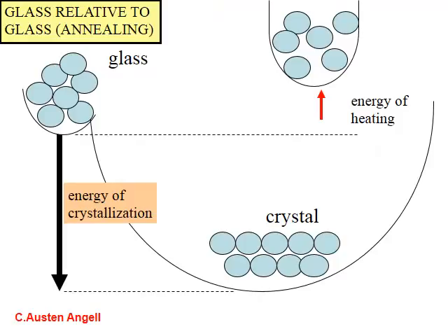Once obtained by quenching the melt, it's a common practice in glass production to bring the glass to a high temperature again, below Tg, in order to relax. Annealing is a routine operation in the preparation of glasses. The structure needs to mechanically relax. A common observation from non-experienced glassmakers is the shatter of a glass piece due to wrong, not slow enough, cooling operations.